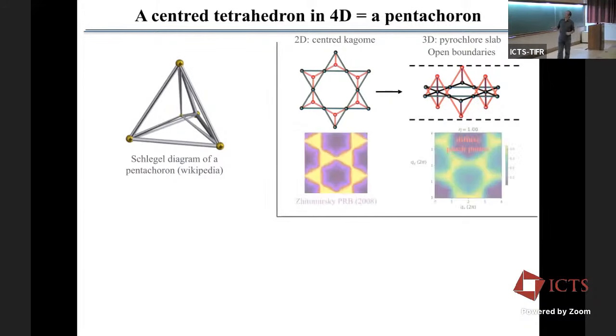And so if you look at the structure factor of the kagome lattice, you have these pinch points at low temperature. You cannot go to very low temperature because you have the onset of a coplanar state, but still, when you are at intermediate low temperature, you have these pinch points corresponding to a sort of Coulomb phase in 2 dimensions.